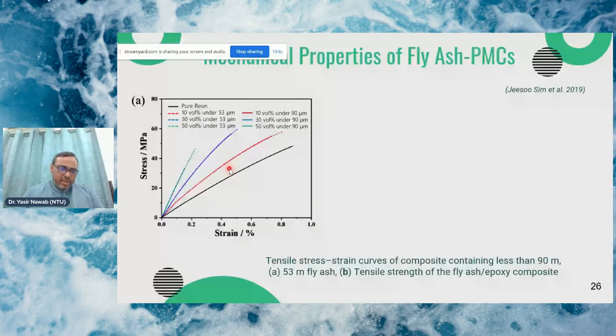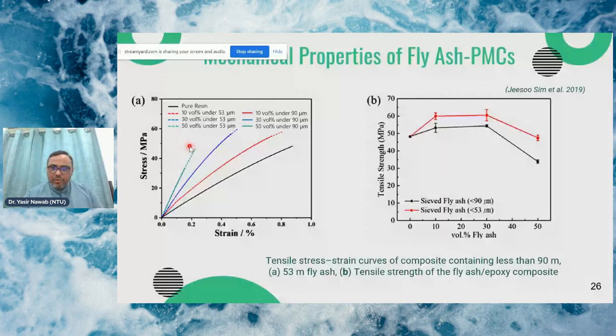So when we add particles, the tensile stress and strain curve is given here. When we add fly ash particles to the polymer, their modulus increases. There is no significant increase in tensile strength. The compressive strength increases, the bending stiffness increases, the impact strength increases, but the impact on the tensile properties is not very significant. However, the modulus increases significantly when we add particles to it. If we change the particle size, of course, for that we will need a further classification, but if we use particles with lesser size, due to their higher surface area, the tensile strength increases as well for different percentages of fly ash.